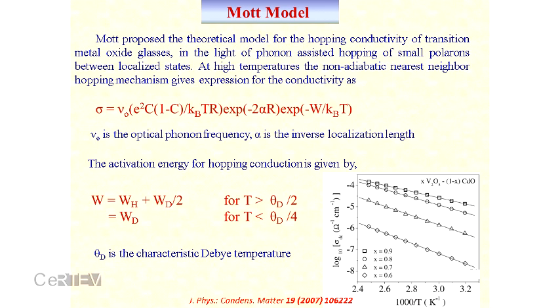Mott first proposed that the hopping conductivity of the transition metal oxide glasses is possible only if they are assisted by the small polaron. If the radius of the polaron is small, then it is called a small polaron. If the radius of the polaron is larger, then polarons can overlap, and it is called a large polaron.